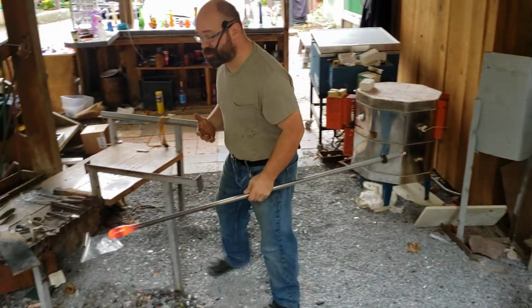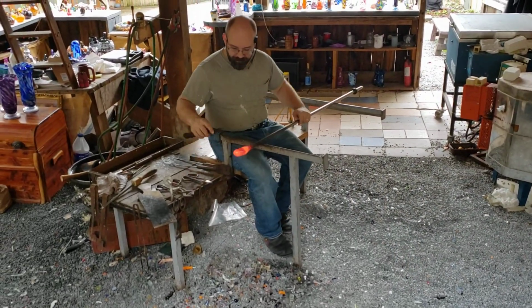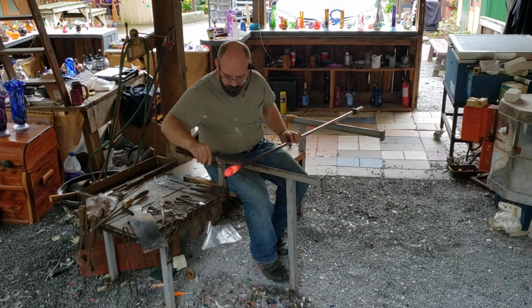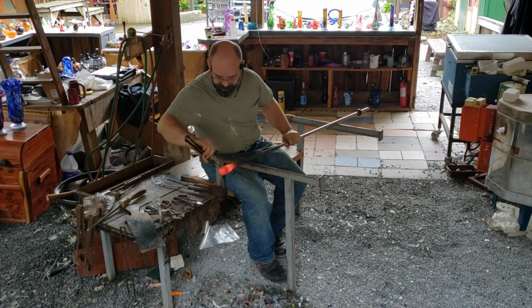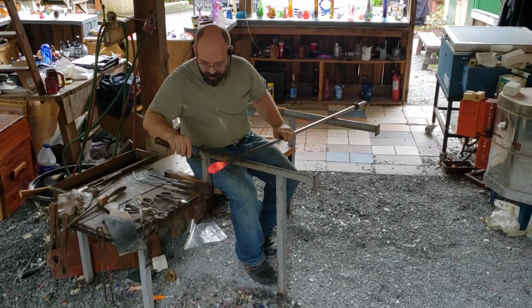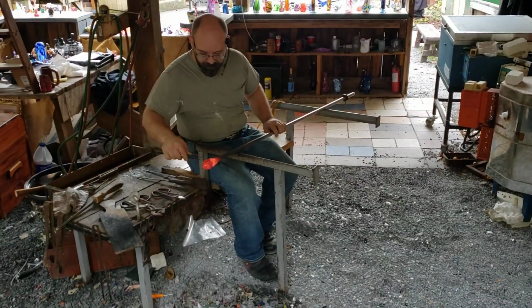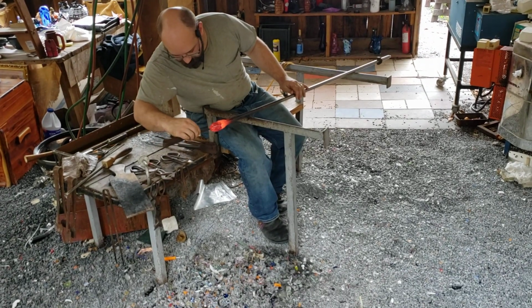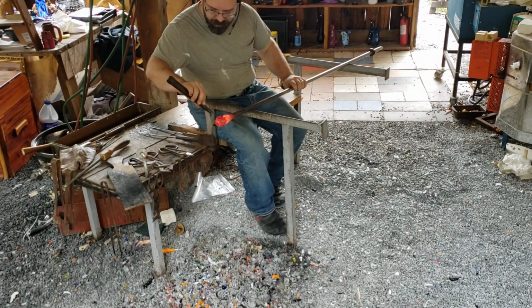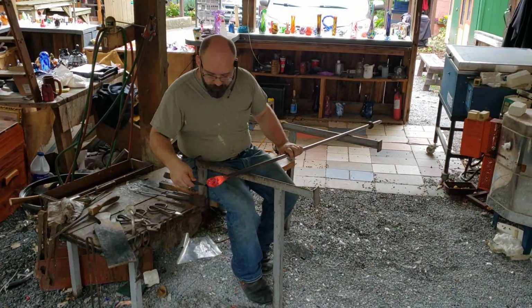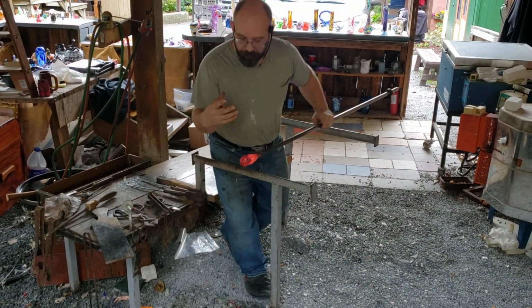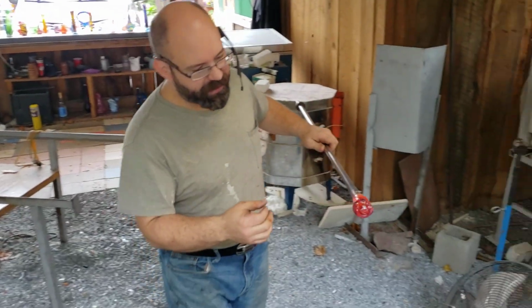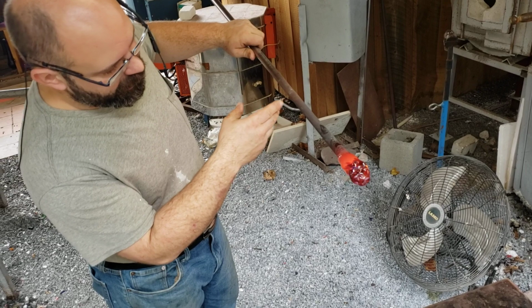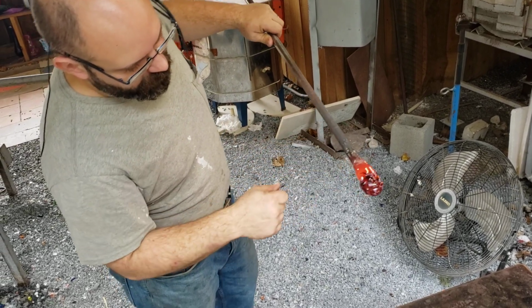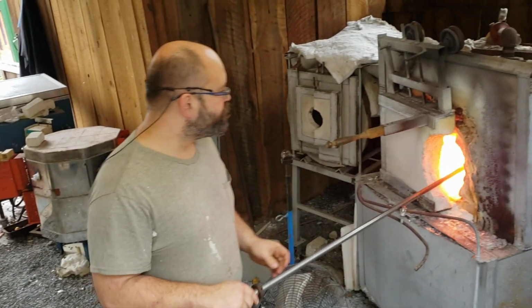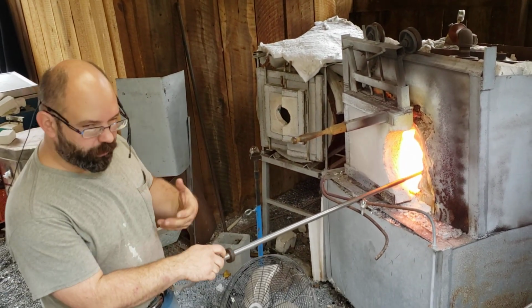I'm gonna add some movement to the color using my tweezers. I'm gonna grab that glass and twist and swirl that color up. You can see a couple different things happening here. Of course, you can see the texture being created, little dark spots where it's cooling off where I grab it. The texture can be an issue. Those large divots, if you don't smooth them out, melt them in, you can have air bubbles form on your piece. You see, we don't have enough glass to make the size piece that we want to make, and that viscous liquid in the furnace is going to not flow into all these little pinches very easily. And so when that happens, it can trap large air bubbles near the surface.